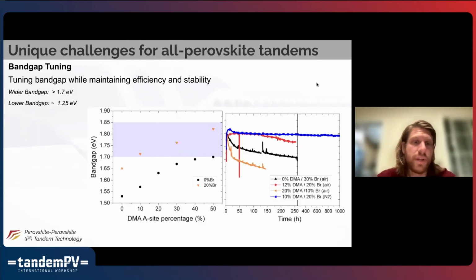On the other side, we have the wider bandgap perovskite. I think we've heard a lot in this conference about the challenges there. I'll just say that there are ways to make wide bandgap perovskites that are different from just increasing bromine content, because bromine content can cause problems. This was also something published a while ago. By incorporating a different A-side cation, we can tune the bandgap independently of bromine, and that lets us get to a very attractive range of band gaps for the all-perovskite tandem with quite a low bromine percentage. And that results in a fairly stable device. This is again, I think 2018 or so, that we did this.